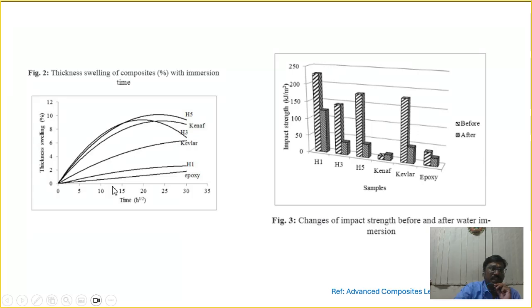The thickness swelling with respect to time also increases up to 20 hours, and above that it is drastically reduced. After that, there is a very important phenomenon you need to know about: how the impact strength and other mechanical properties are deteriorated because of the water absorption. The impact strength is higher without absorption of water. With increasing water absorption, you know that H3 and H5 absorb more water molecules because of high diffusivity, compared with H1.